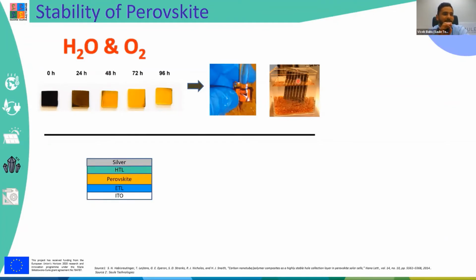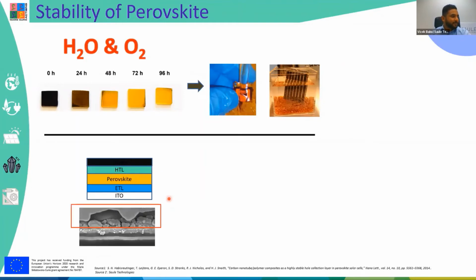And also, other than the external factors, it's important to consider the internal degradation factors. For example, like I told you, the perovskite consists of these cations and anions, which have ionic bonds, which can have vacancies or interstitials. These ions can just move around the perovskite crystals. Sometimes they go up and react with the metal electrode, and it basically insulates it, and you don't have a functioning solar cell anymore. You can see this is a cross-sectional image. You basically slice the device and you can see the metal electrode eaten up by these ions.